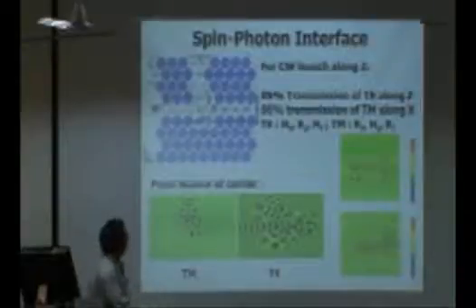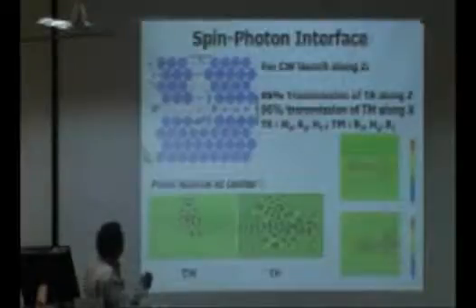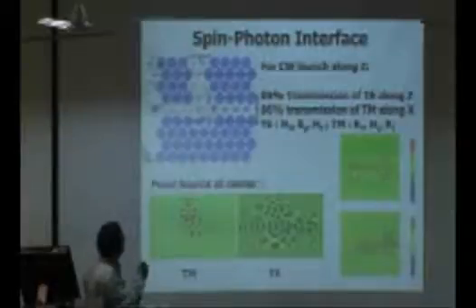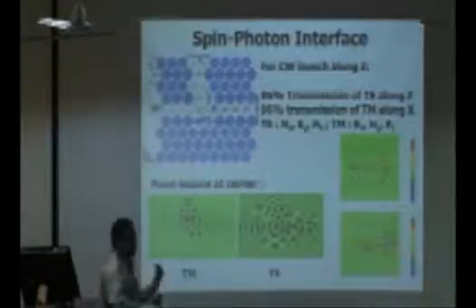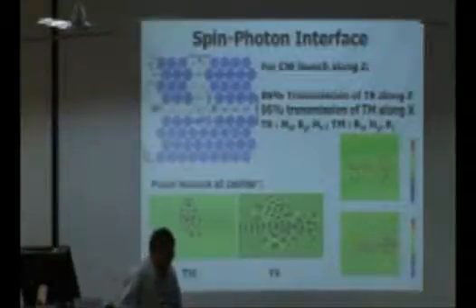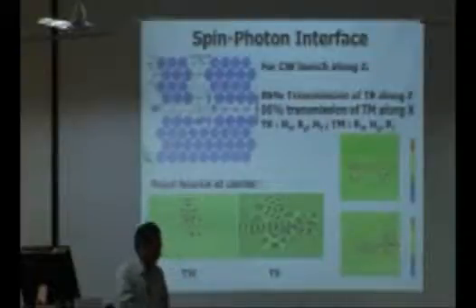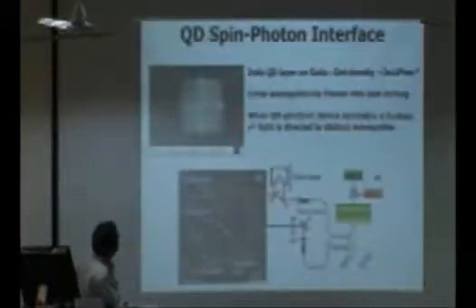So what we designed is photonic crystal structures where, for example, in this case, the TE component travels along the Z direction, which is horizontal, and the TM component preferentially goes in the vertical direction. By studying these two, we can back calculate the spin state of the quantum dot. That's the idea. As a proof of principle, we did some experimental studies, where we have a quantum dot at the center of the structure with 4 waveguides in 4 directions. We can label them top, right, left, and bottom, and these are the output couplers.